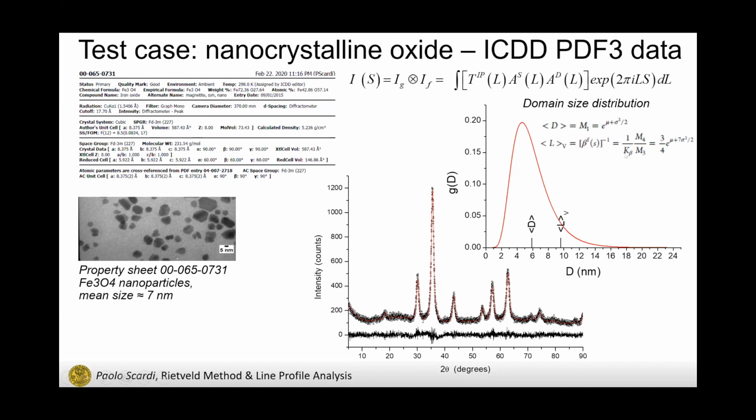Actually, the constant is 4 divided by 3, the inverse is 3/4. So clearly here you see that what you get is different, and in general, given a distribution which is skewed, you will have quite a difference between the arithmetic average, as you see in this picture, and the Scherrer width. They are different, they must be different.